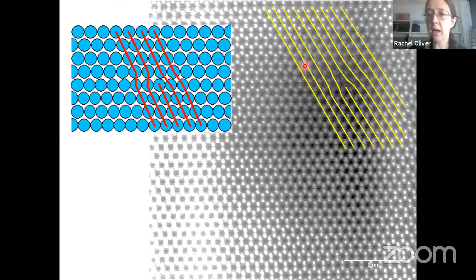This is a transmission electron microscopy image of gallium nitride, and we're looking at the material in atomic resolution. So each of these bright dots is a column of gallium atoms extending into the page, not actually a single atom, but nonetheless, we're seeing here the atomic structure. And you may be able to see that there's something odd going on over here. And if I draw in the positions of the planes of atoms running through the gallium nitride crystal, what we find is this dislocation structure that I illustrated earlier, a half plane of atoms that stops in the crystal, with the other planes of atoms bending around it and distorting the local crystal structure and the atomic bonding.